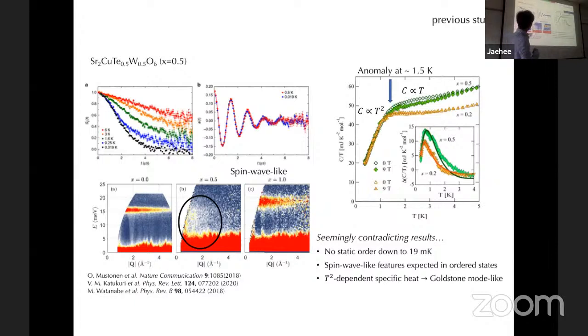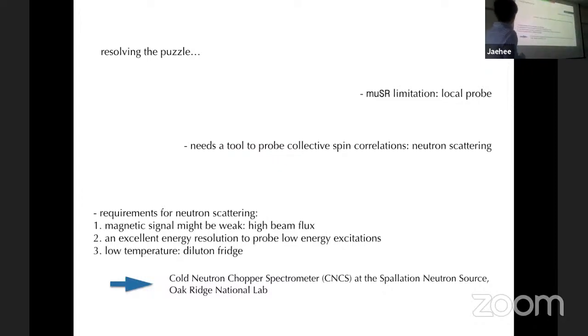And then when people do neutron scattering measurements, I think this is Katukuri. And so at the two endpoints, you have this magnon dispersion here. And here also, if you look closely, I'll show you my group's data is much better. So you have this similar magnon-type dispersion with the excitations here. But it's broad in energy, a little more diffuse than the two endpoints. So you can see here, if you look at the specific heat and inelastic neutron scattering, you can see, oh, this is spin wave-like. But then if you look at the muon data, no, there's no ordering. So there's a controversy there. That's why we did neutron scattering. We jumped into this field and tried to figure out why this seemingly contradicting experimental data.